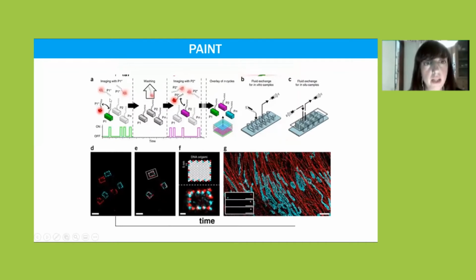Okay. Because it relies on these oligonucleotides, you can work with many different sequences. In theory, well, many of them. Then with just one color of the imager, you can have many structures of interest labeled in your sample. So each time, like here, you use microfluidics. You first image with imager 1, so that it binds to the structure that has the oligo complementary to imager 1. Then you wash in the imager 2 that binds with the one that has the imager 2 complementary sequence, and so on. You can do this n times. And then only using the same fluorophore, you can image many colors.